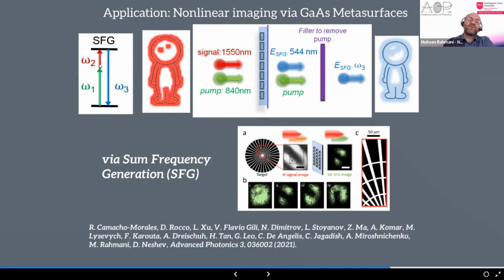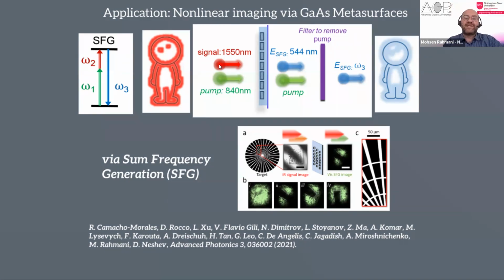It means that in addition to the near infrared light at omega, we will have one pump, which is still in the near infrared, but it is just to enhance the low intensity of the near infrared light. And finally, we will get the signal in the visible range. So it means that by these nanoparticles and metasurfaces, and by the right design and using the right pump, you can take a very weak near infrared signal, convert it to the visible range, and see the light in the visible range, which has a lot of applications, which we are working on at the moment.